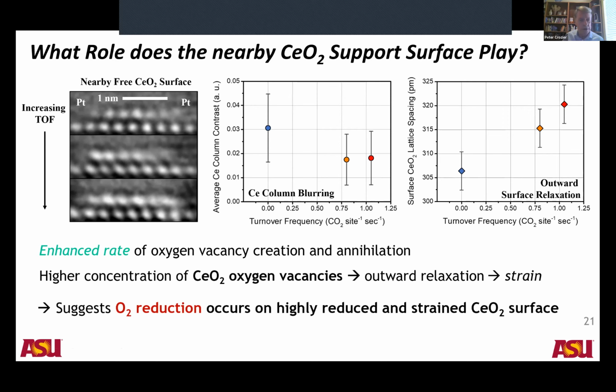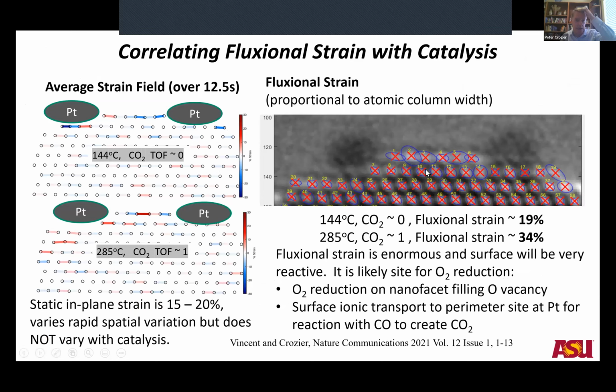So what he's got now is that these fluxional behaviors that we're seeing at the surface of the ceria and on the platinum nanoparticles directly correlates with the catalytic functionality that we're interested in. And there was also an outward relaxation that he measured of about 15 picometers here, which is also associated with turnover frequency. So I think what we're getting from this is summarized in this slide here, which I probably don't want to go into in a lot of detail in the interest of time, but essentially what we're finding is that